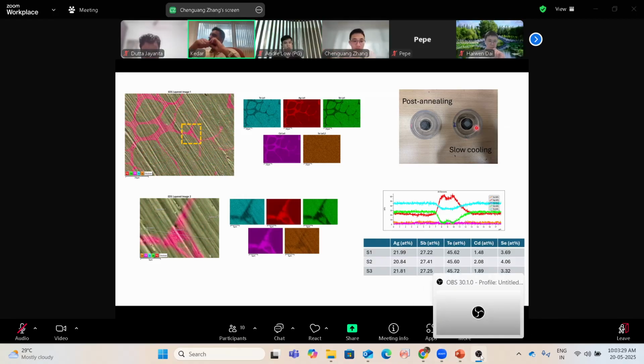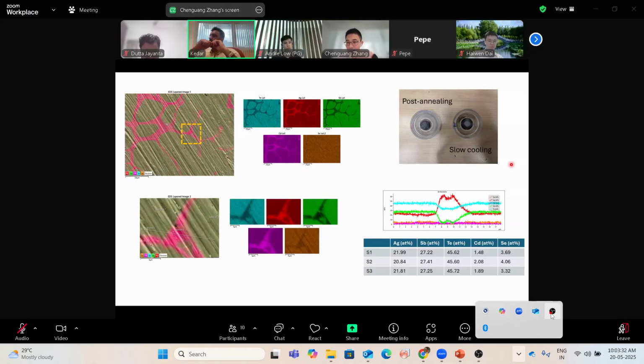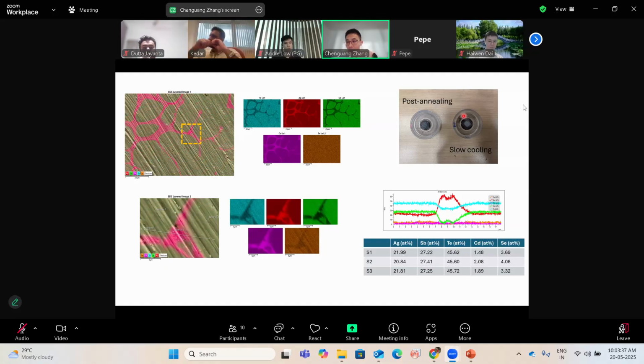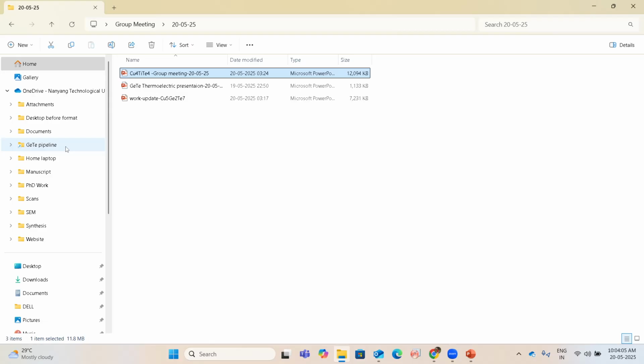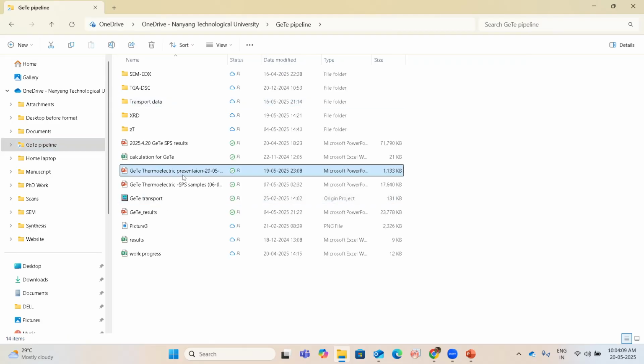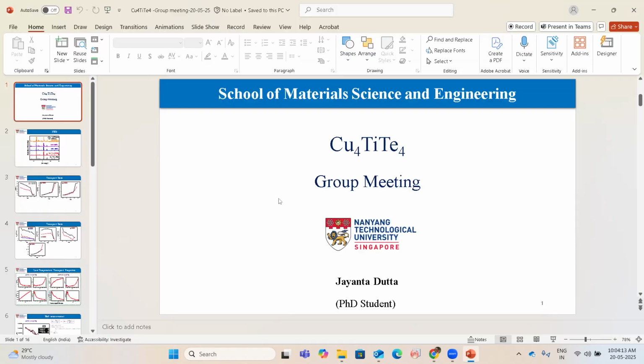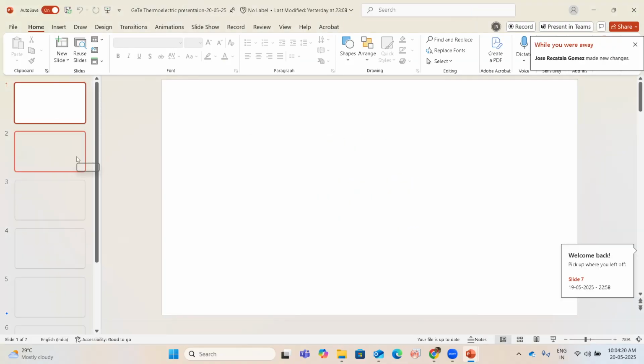But how does it compare to a standard, regular sample without slow cooling? So you're comparing, it's almost the same as the slow cooling. But the microstructure would be the same as the post-annealing sample? The microstructure is the same for all of them? No, actually no. The post-annealing sample is quenched, then you put it in the furnace for post-annealing. But slow cooling is just cooling step by step down to room temperature. You can see the interface layer here is almost like our previous work, so the microstructure won't change.